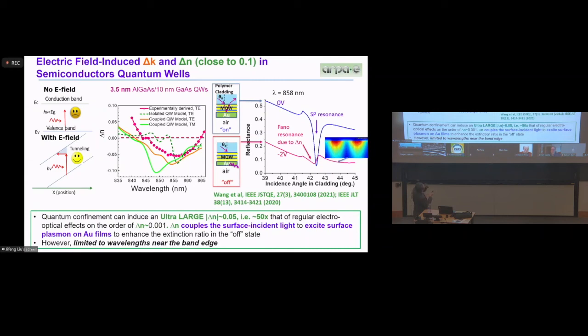This is about 5 micron in diameter. And basically, you can see that when there's no voltage applied here, no electric field, the quantum well is transparent. The light hits the gold film on the bottom and mostly gets reflected back. So basically, it's transparent overall.